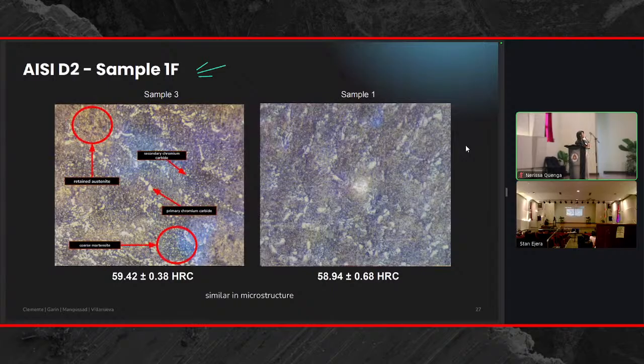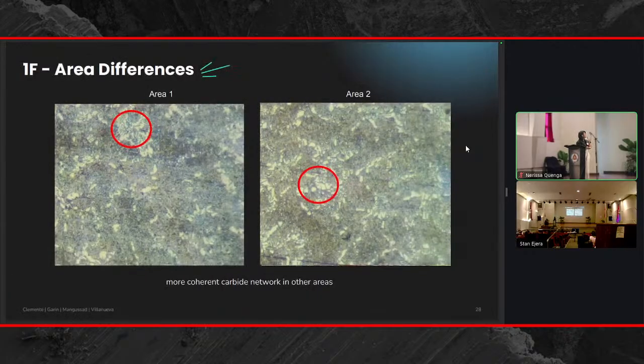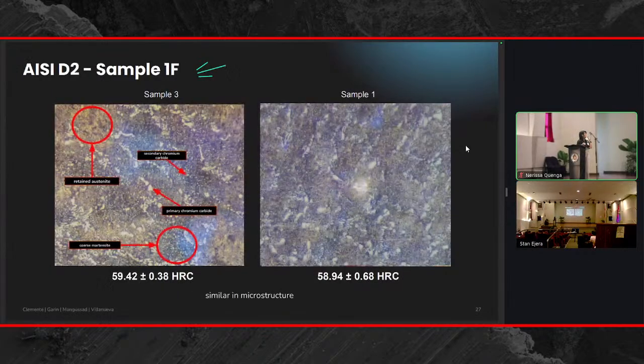So here we have a comparison of the microstructures of sample 3 and sample 1, the first failed sample here. Similar po ang hardness nila, medyo similar din yung microstructure. But if we compare different areas of the sample 1F, we can see that mas coherent ang carbide network in some areas, while in others, it doesn't seem like the carbides have precipitated in much of the grain boundaries yet. So comparing these two, at least we can say that there may have been other factors as to why